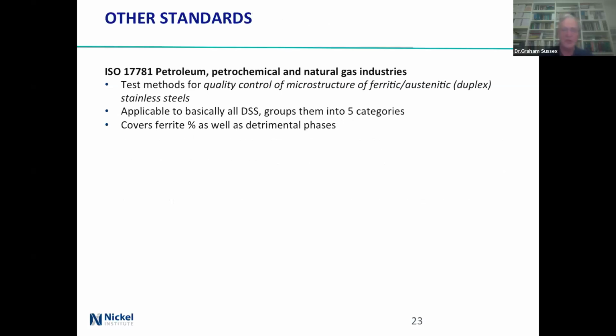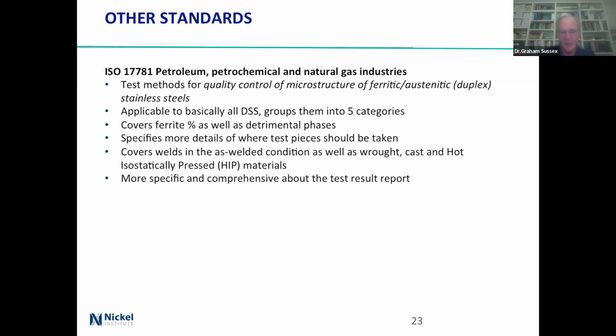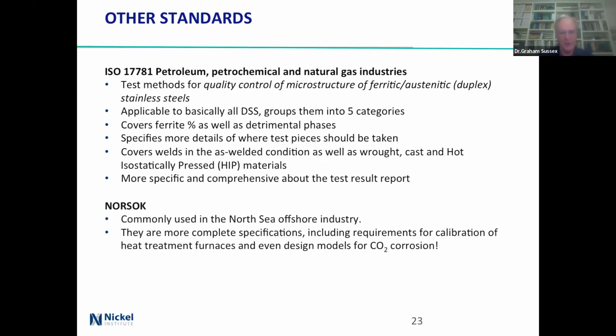There's an ISO 17781, which the oil and gas people use, and that basically works for all duplex stainless and puts them into 5 categories. So we've got 5 levels. It also has the ferrite levels, as well as detrimental phases. It specifies a lot more details about where you take it from, as in the thickest bit, at bends, near welds, etc. It will look at covering welds in the as-welded condition, as well as wrought, cast, HIP, isostatically pressed, and it's a bit more specific and comprehensive about what you've got to put in the test result reports. You've got to report everything. It's not just pick one, but that's it. The Norsok, the Norwegians, commonly used in the North Sea, very good standards, but it is very tightly tied in with that.